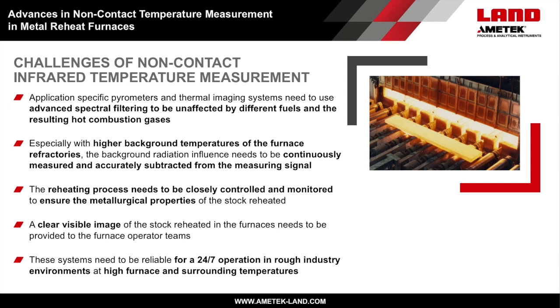Especially with higher background temperatures of the furnace refractories, the background radiation influence needs to be continuously measured and accurately subtracted from the measuring signal. The reheating process needs to be closely controlled and monitored to ensure the metallurgical properties of the stock are reheated homogeneously. A clear visible image of the stock reheated in the furnace needs to be provided to the furnace operator. These systems need to be reliable for 24/7 operation in rough industrial environments at high furnace and surrounding temperatures.